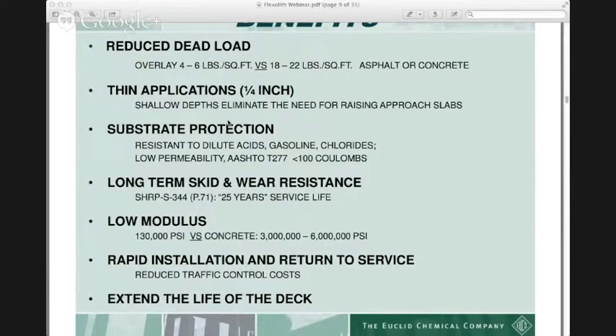The substrate protection, of course, it is resistant to dilute acids, as I mentioned earlier, gasoline, chlorides, low permeability, again, much less than 1,000 coulombs, and sometimes even less than 100 coulombs for the initial 4 or 5 years. Long-term skid resistance and wear resistance, as indicated by that SHRP study done a number of years ago, over a 25-year life cycle. So it does hold up extremely well from a skid resistance point of view as well.